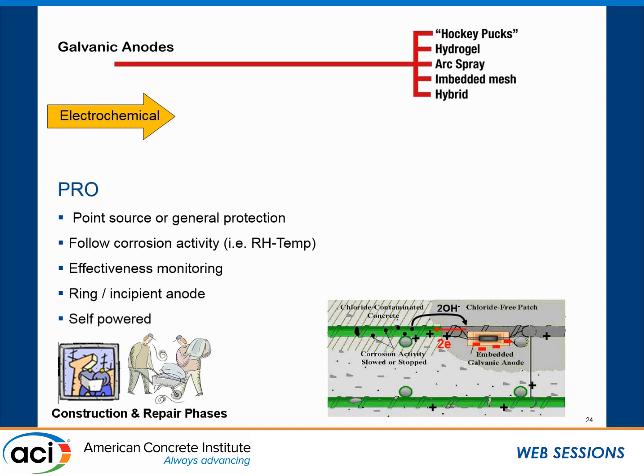And they're self-powered. They're consumable. I got something that's going to corrode away, and eventually it will wear out. Do they passivate? In that chemical environment, you have to put some stuff in there to keep them active, but often that stuff that you're putting in there may wind up leaving corrosive material behind when the zinc's gone. They attract chlorides as they corrode. And I have to excavate to install them. And oxidation buildup. However, with things like arc spray, flame deposited zinc on the surface, that's pretty cool technology. It changes the appearance. I have to have dry concrete, and it's some pretty specialized equipment, but it's been pretty effective.